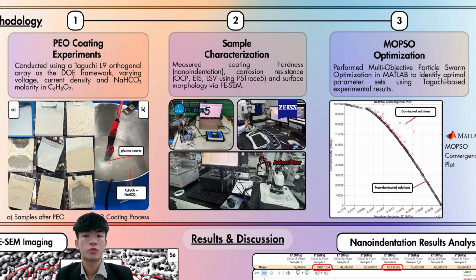Once the initial experimental trials in the Taguchi array were completed, I moved on to the second phase of the methodology, which was sample characterization. In this stage, 3 main types of characterizations were carried out. Firstly, FESEM imaging was performed at 3,000 to 20,000 times of different magnifications to observe surface morphology and, most importantly, to identify the presence of uniform nanoporous features which were ideal for this type of coating.